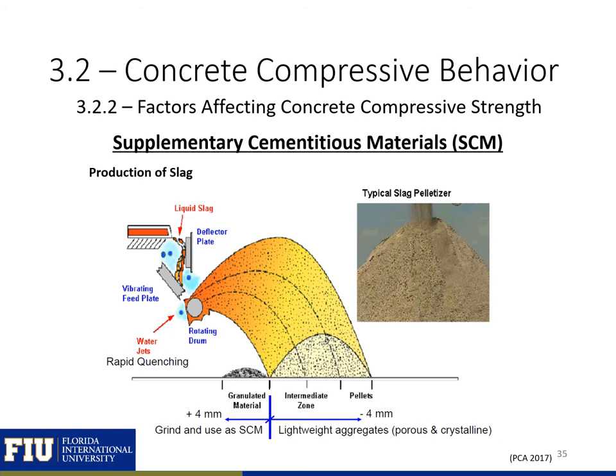The way the slag is processed will affect how it can be used. The liquid slag is cooled rapidly using water to ensure it forms the amorphous phase necessary for hydraulic benefits. Crystalline slag exhibits little or no cementitious behavior. This process separates the slag. Expanded slag can be used as lightweight aggregate. Granulated slag is ground and used as a hydraulic SCM.